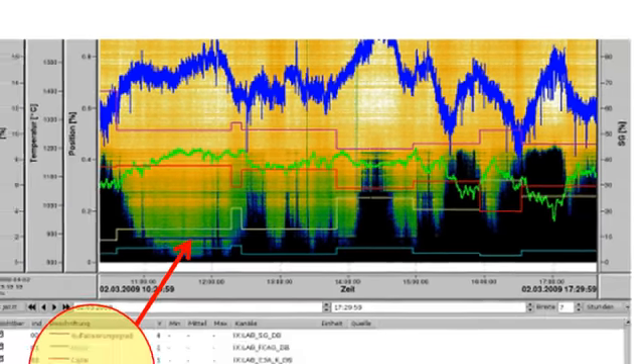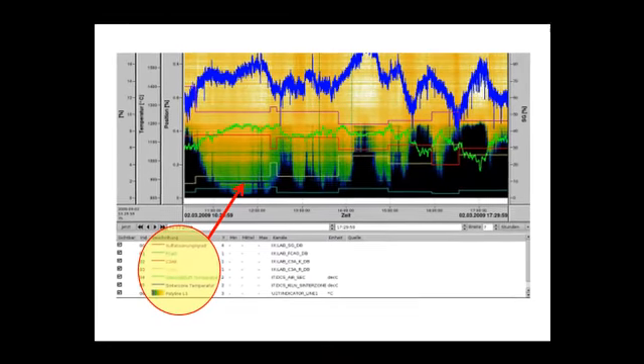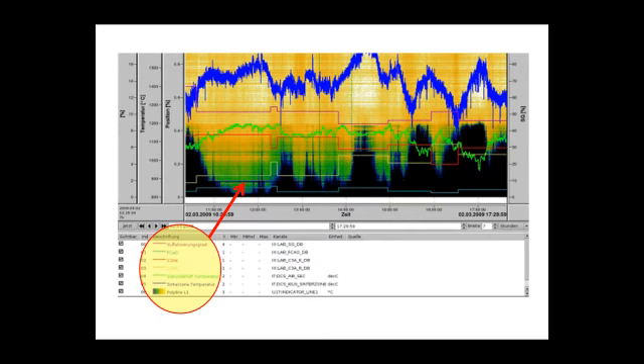The burning of the clinker takes place at different positions in the kiln. Therefore, the classic sintering zone parameter is only of small use in this kiln with a high rate of alternative fuels. But by correlating the process variables with the polylines, the process expert gets a clear indication of the influence of the flame on the clinker quality.